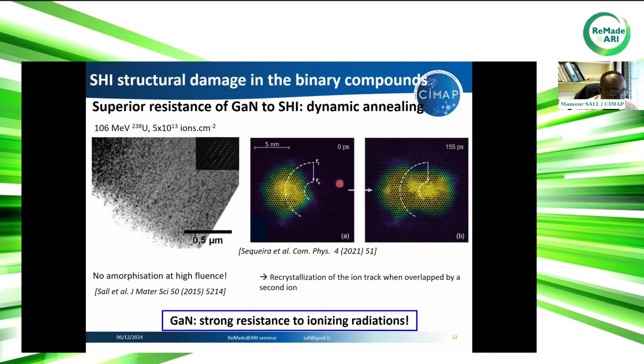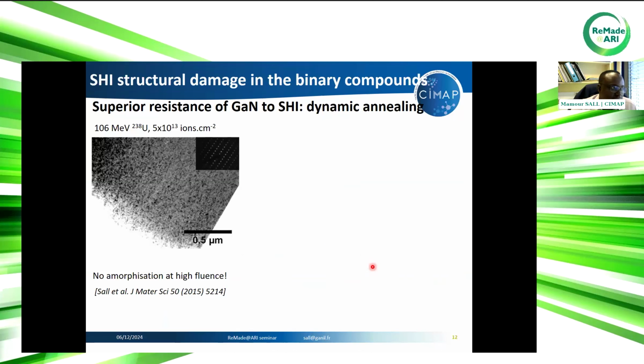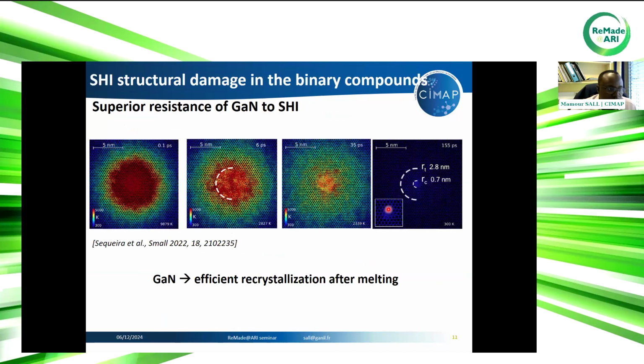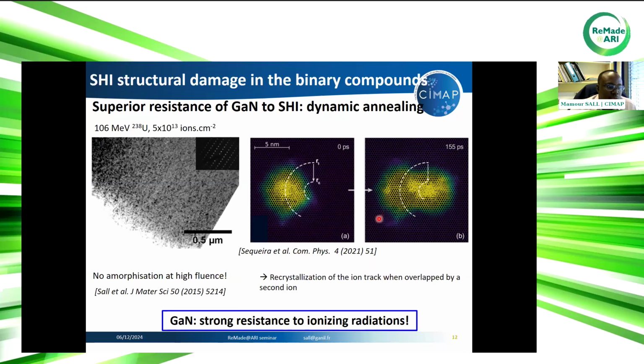So what happens is we create a second track here, which is amorphous. But at the same time, the pre-existing track is annealed by the second ion. So in fact, when we have overlapping of tracks, we create recrystallization due to the second track. So this is why gallium nitride is in fact very resistant to ionizing radiation. First, we crystallize the track by this process, but also when we overlap tracks, we have this recrystallization which is done by the second ion, let's say.